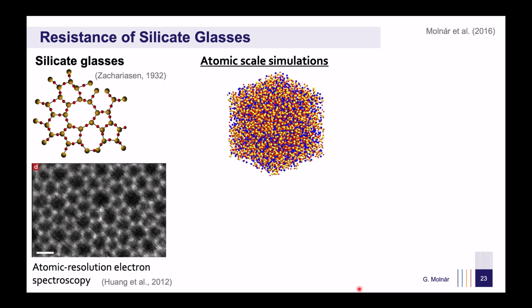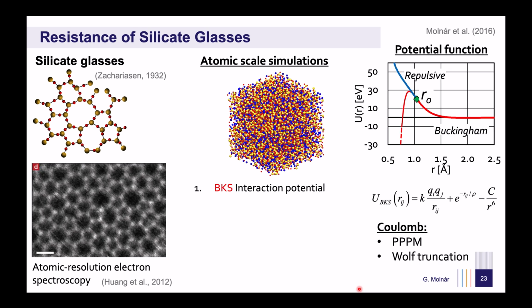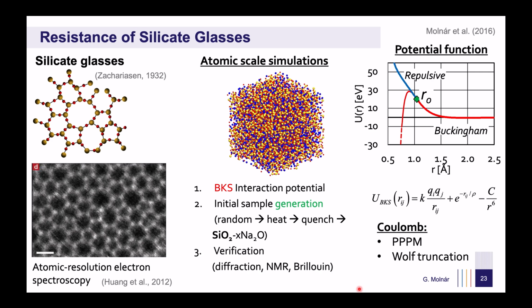In this study, we use molecular dynamics and molecular statics to investigate the mechanical response of silicate glasses. We employed a BKS pair potential consisting of an exponential and a hyperbolic term, with Coulombic interactions handled using long-range solvers or Wolf truncation methods. The glass samples were generated randomly. They were first heated above the glass transition temperature and then slowly cooled to form a stable structure. Finally, we verified the atomic structures using experimental measurements to ensure their accuracy.